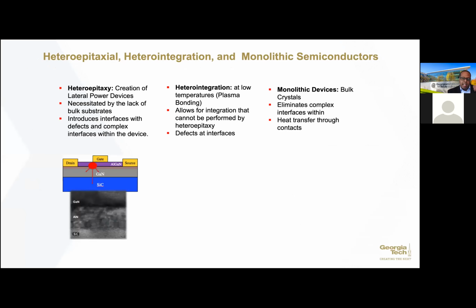So when I look at these structures, the types of structures we'll have are what we call hetero-epitaxy. So this is where I have to grow a material on a non-native substrate. And the magic that is done here in terms of the device growers, because of the lattice mismatch between a material like gallium nitride and silicon carbide, you basically put another layer in between, in this case, aluminum nitride. And this has been done for a while. Hiroshi Amano at Nagoya University in Japan, this is what he actually did in his PhD thesis in order to grow electronic grade gallium nitride.